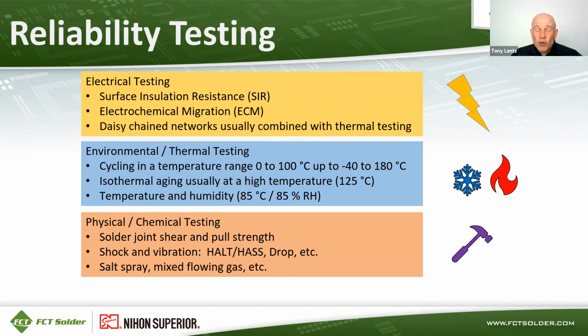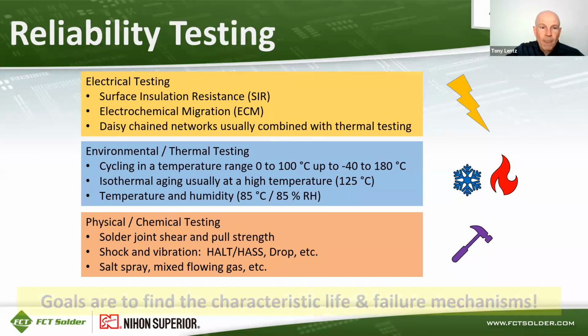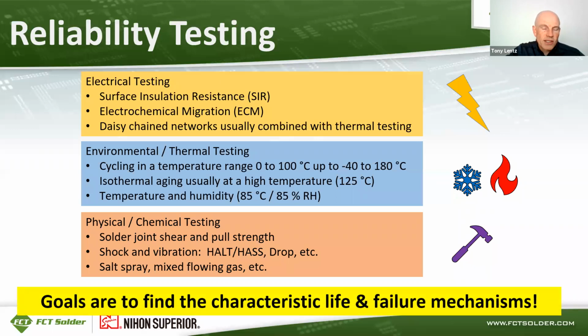Mixed flowing gas testing is quite an aggressive test. It helps to find creep corrosion and things like that with different metal finishes that are used on the circuit boards and the components in the solder joints. And then we might combine some of these different methods together. For example, daisy chain electrical monitoring might be done in combination with thermal cycle testing and shock and vibration in some cases. The whole goal of all these tests is to try to accelerate the failure of the circuit boards to find the characteristic life, and then also to determine what the failure mechanisms are, or where the weak spots are in the electronic assembly.